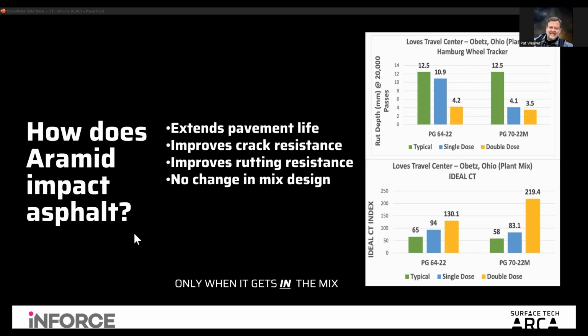12.5 again on a 70-22. So you can see where the polymer modified binder didn't have an impact on the rut resistance by itself. When you add a single dose of fiber to that, you can see it drops into the same range as a double dose would do in a non-modified binder. And then you go to the double dose, doesn't have a big impact on the modified binder.